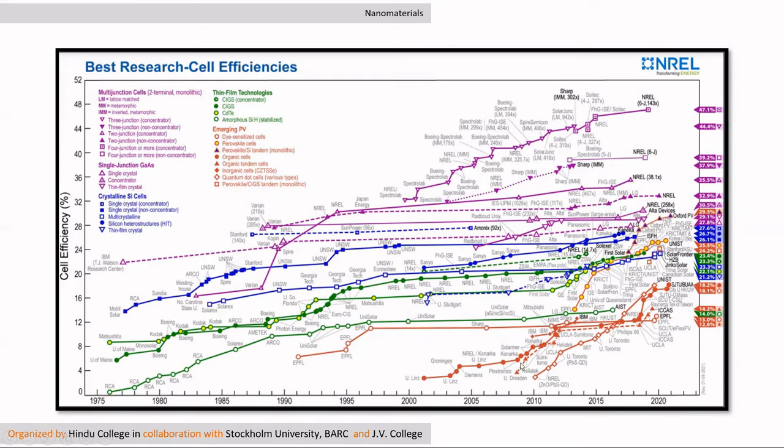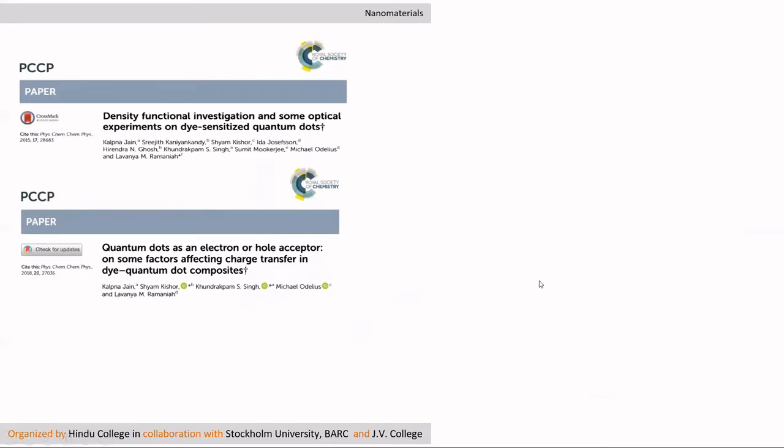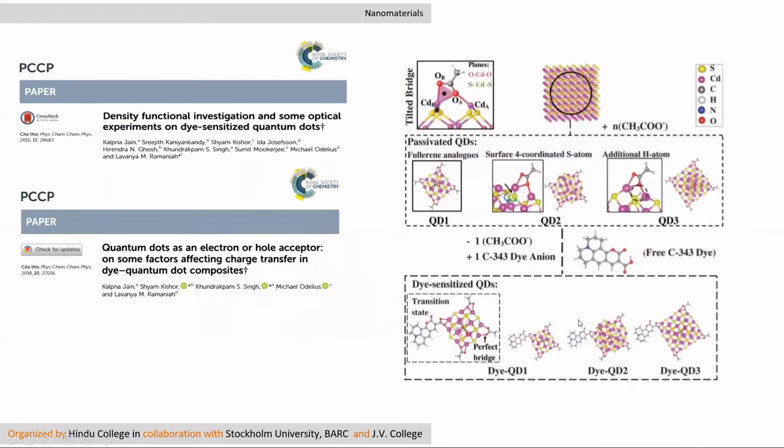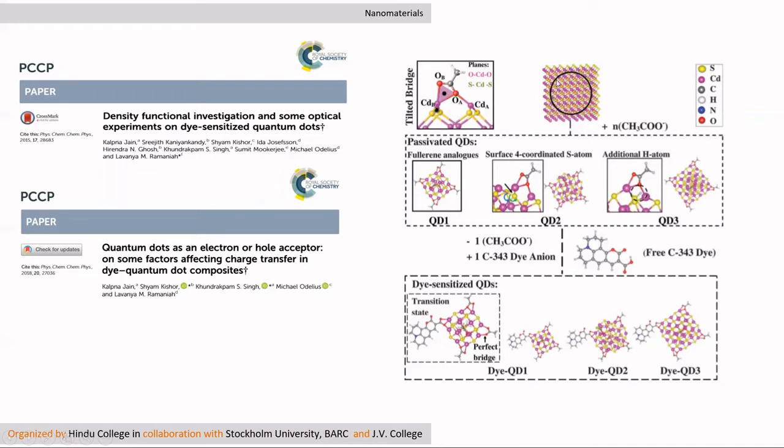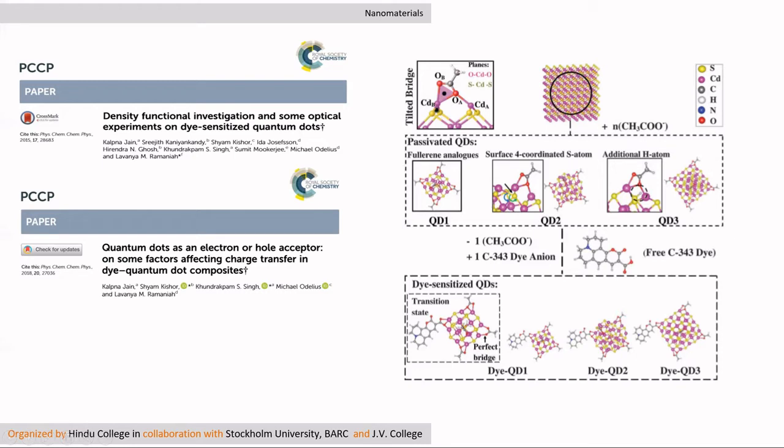And in this area, we also model a system that is dye-sensitized quantum dot. The quantum dot was created by bifurcating a small portion of the bulk material in the spherical shape as much as possible. But when you do the bifurcation, when you do this cutting, it results into formation of dangling bonds on the surface. Dangling bond means normally the ions which are in the bulk, for example, this case has coordination number 4. Cadmium is bounded by 4 sulfide ions in the tetrahedral fashion. Sulfide ion is bounded by 4 cadmium ions in the tetrahedral fashion. But the ions which are present on the surface has coordination number less than 4.